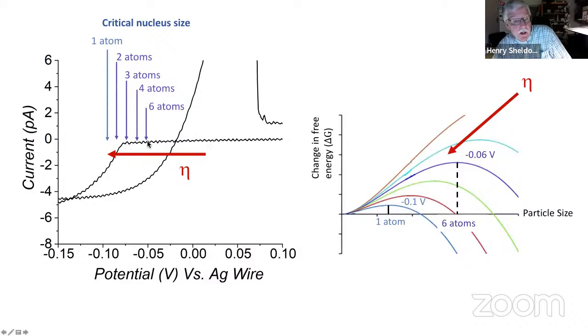When I'm doing these nucleation measurements, I do a step potential. I step to here, and that's a low overpotential, 60 millivolts. Here that corresponds to the critical nucleus being 6 atoms. That's this, going down from here to the x-axis. So we know the intercept, we know where the maximum in the free energy curve occurs, and you can do this atom by atom. So this is what it looks like. You go to larger overpotentials, the activation barrier gets smaller, the critical size radius gets smaller. You get out to 1 atom.